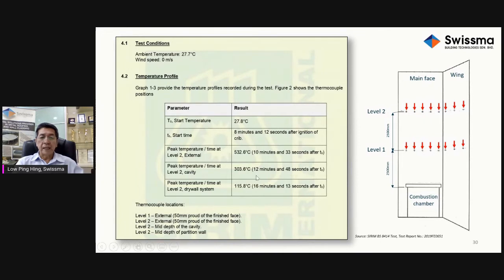So the peak temperature at level 2, this is at 303, because this is at a cavity, sorry. This is an external cladding. This is the temperature measurement inside the cavity. And that happens 2 minutes later. And they also measure the temperature inside the drywall, which is at 115.8 degrees Celsius, which is a lot lower than the external cladding temperature.